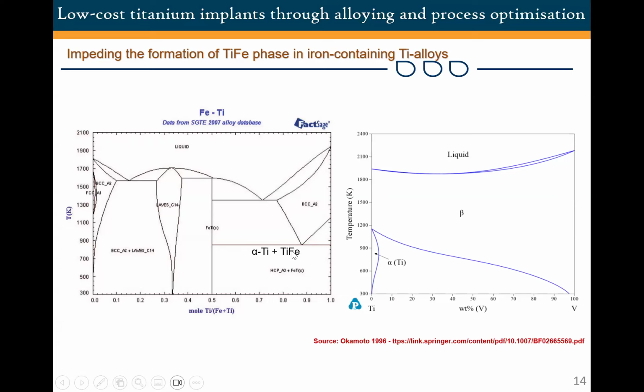And when you have this TiFe intermetallic compound, it has negative effects on the mechanical performance or mechanical properties of the alloy. It's too hard, very brittle, it's not ductile. And if you use that in service, for example, as an implant, it could fracture in a brittle mode, and that could really endanger the life of people. The same thing would happen if you had to use it maybe for aerospace applications. So even though efforts have been made to replace vanadium with iron, it turned out that it's not an entirely good idea, except if you can limit the amount of iron to about maybe 1.5%, according to some of the work previously published in this space.